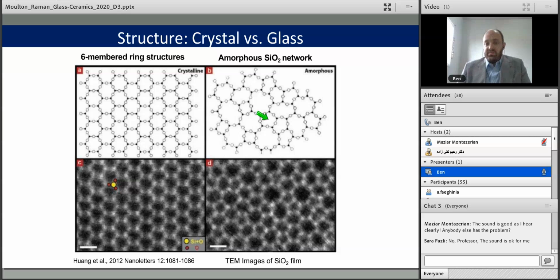It would be another 50 years before any developments were made, and it would be another 80 years before we actually visualized this. On the bottom are transmission electron microscopy images of a bilayer of silica that was crystallized. This group, Huang et al., who published this letter in 2012, were actually working on single sheets of graphene layers, and they accidentally sputtered some silica on top of the graphene, and it happened to produce these beautiful TEM images showing the six-member rings here, exactly as Zachariasen predicted in 1932. They also found non-crystalline regions with different numbers of five-member rings and six-member rings here, similar to what Zachariasen had hypothesized.